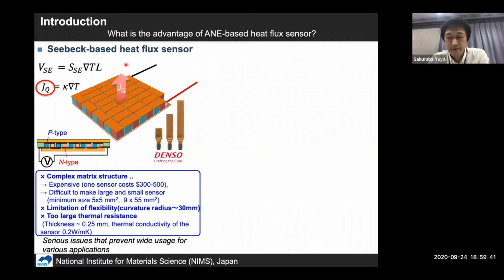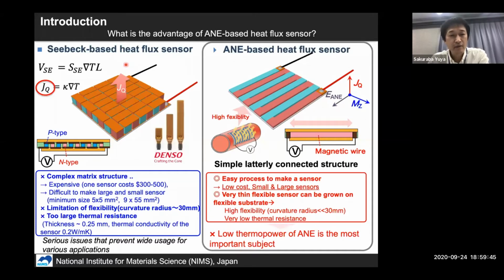That is the reason why this Seebeck-based heat flux sensor has been used only in a limited way. However, we believe we can overcome this kind of problem by using the anomalous Nernst effect-based heat flux sensor. Because this sensor has a very simple structure, it is very easy to make the thermopile structure. So we believe we can reduce the cost of one sensor. And it is not difficult to make smaller and larger sensors using the anomalous Nernst effect. And we can reduce the total thickness of this sensor, so we can obtain much higher flexibility and low thermal resistance. So we believe the anomalous Nernst-based heat flux sensor will be a very promising application.